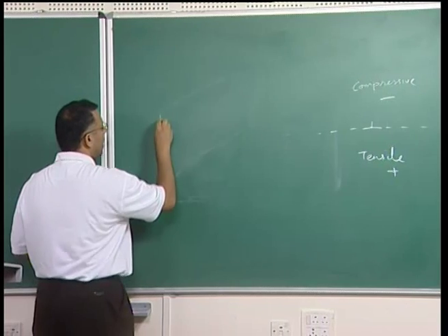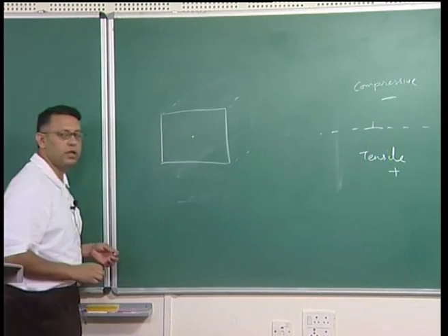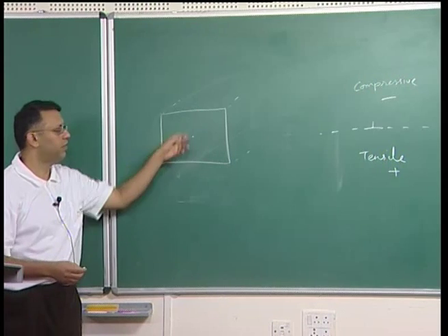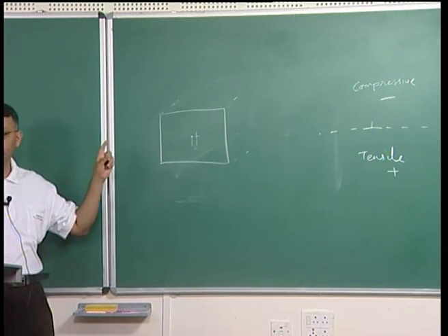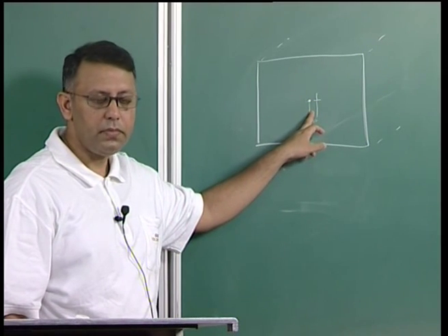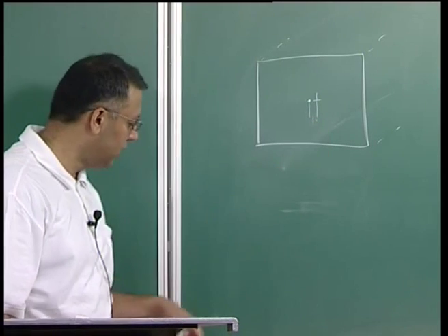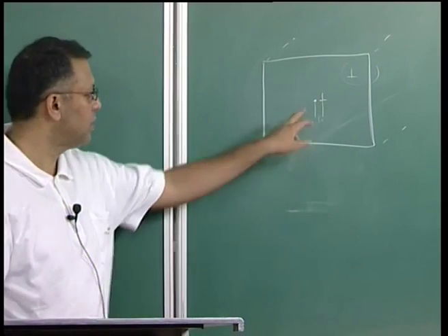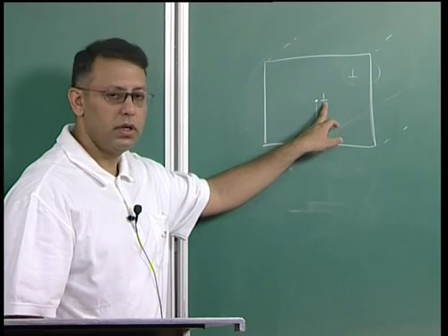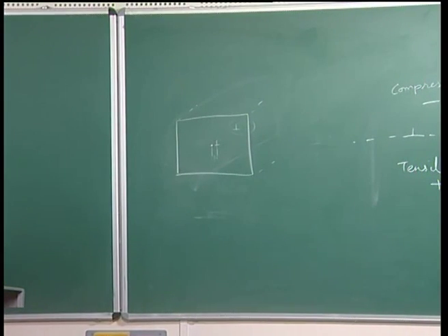Suppose I just for now take a symmetrical body, where the crystal goes along the z direction. Right at the center of the body the dislocation will experience no image force, because all the faces are equally distant. But suppose I consider a dislocation at a distance b from the center. The image force strength is going to be very, very weak, because this surface is not very different in distance from that surface. Even if this little weak force is larger than the Peierls stress, then all dislocations will leave. Suppose you consider a dislocation here, obviously it is closer, so it will leave. This is the worst case scenario or near worst case, because the center of course feels no force. If this dislocation can leave the crystal, then I assume that all the dislocations would have left the crystal and this crystal will become spontaneously dislocation free.